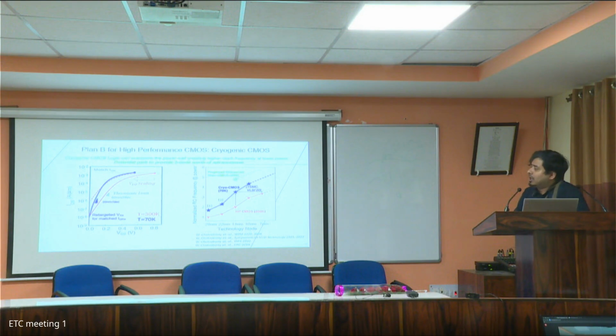There are multiple reasons. At low temperature, you actually get those steep slope transistors. Your mobility goes up at low temperature because now you have less phonon scattering, and there are multiple other advancements that come automatically when you operate a transistor at low temperature. With all those combined, the best way to read this graph is that if you pick 14 nanometer technology, and you just operate it at 70 Kelvin, it gives you the same amount of benefit that a 7 nanometer technology will give you. So basically, this cryogenic CMOS is a path to get two nodes worth of advancement without actually doing anything, just operating at lower temperature.